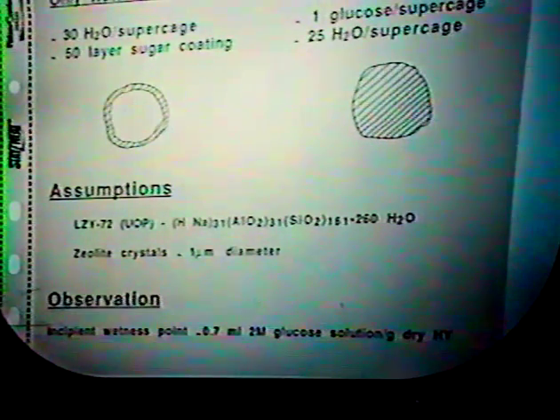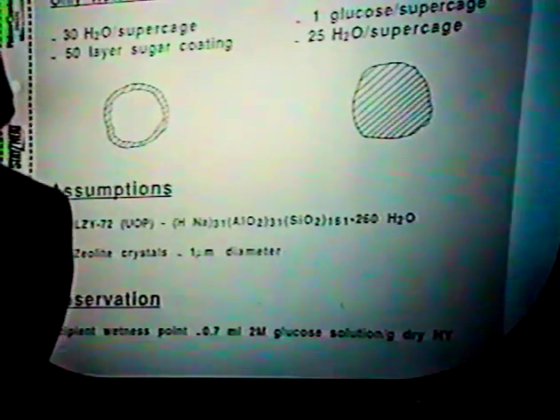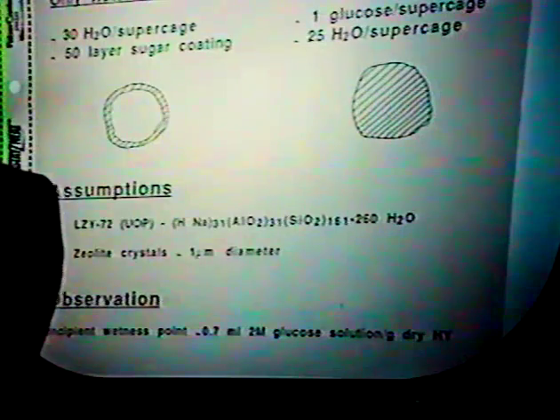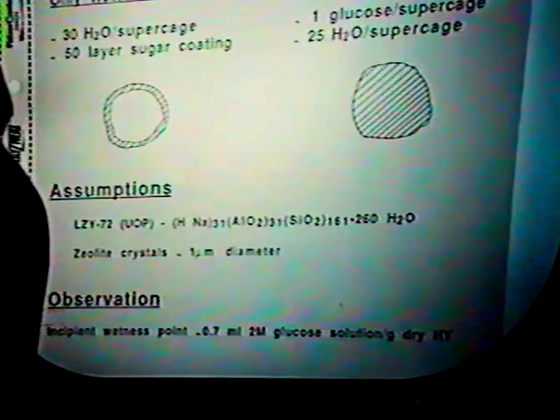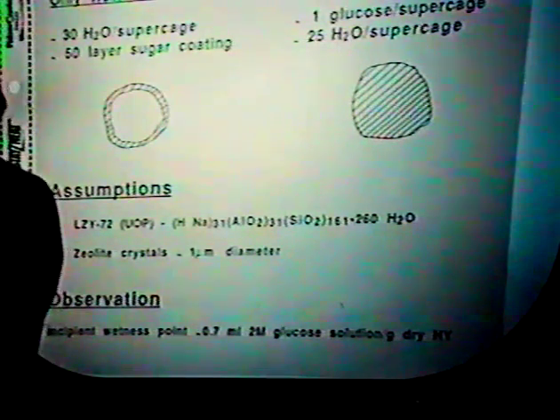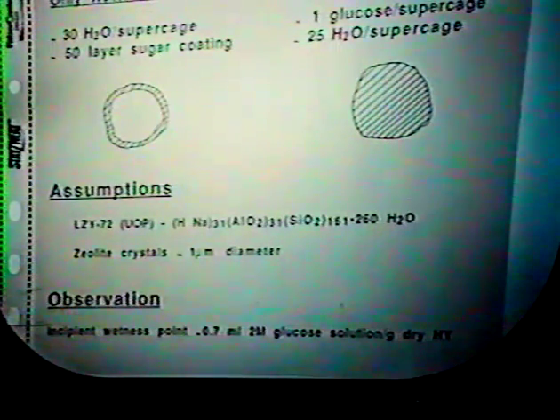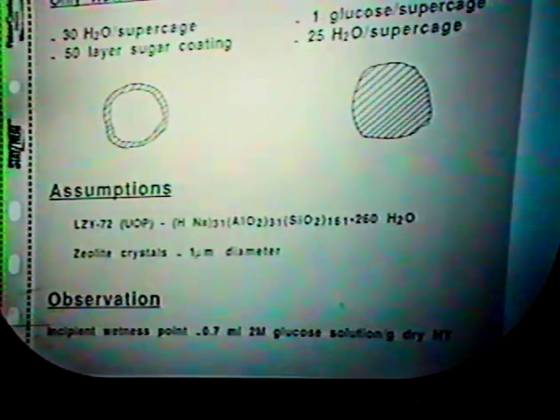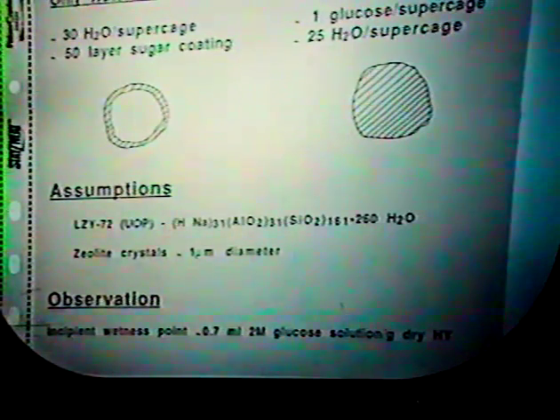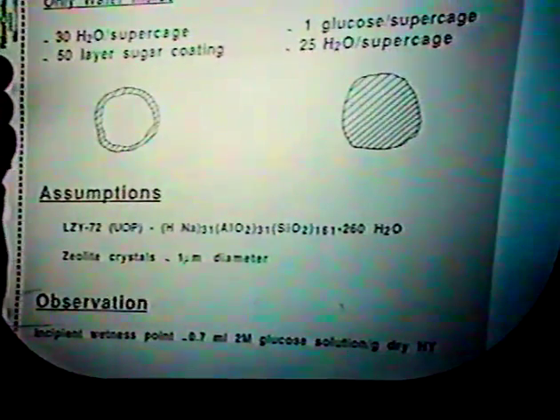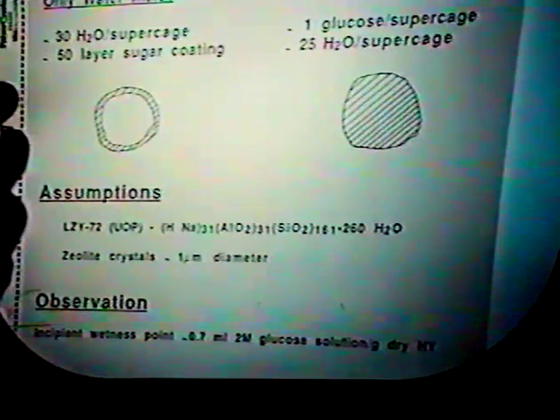The incipient wetness point for this material is about 200% of the solution needed to saturate the pores. If you dry the material and start adding solution, watching for the powder to just turn wet, you can add about twice as much water as needed to saturate the pores, and some of the reaction measurements have been done under those circumstances.